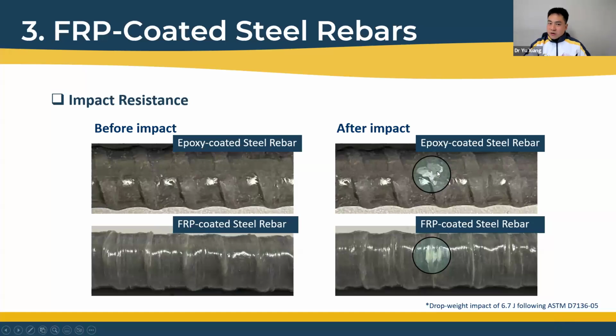After the impact, as expected, the epoxy coated steel rebar had its coating layer peeled off, and a large area of the substrate was exposed. Because the FRP coating layer has several layers of fibers stacking one on another, only the most exterior surface was damaged, while the deeper layers remained very well.